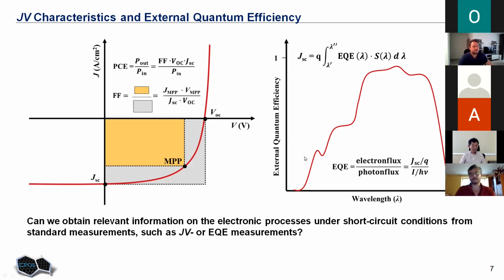Another important parameter is wavelength, like spectral response of solar cell. Obviously, it depends on materials which we use. We will have different widths of this region of photosensitivity, let's call it like this. And this external quantum efficiency is technically the ratio of the number of photo-generated charge carriers which form photocurrent in external circuit under short circuit conditions. So defined by this numerator, we have short circuit current divided by elementary charge, gives us number of charge carriers, divided by the number of photons of monochromatic illumination at each wavelength, which are incident on the solar cell. So that is another very important and commonly measured parameter.